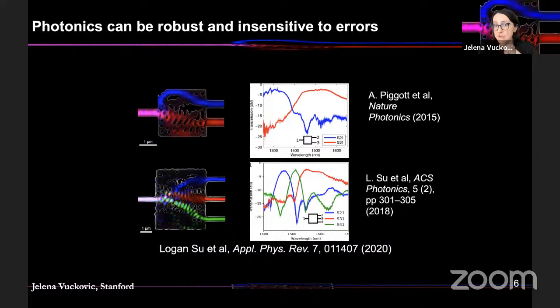And we were successful in that. Actually, here on the right, you see demonstrations. So these are measured transmission characteristics for many different devices of this type, fabricated with the same parameters. And although our process is not perfect, we don't really need to tune any of these elements. When we measure transmission characteristics and plot them together on the same plot, they all line up on top of each other for both of these blocks. So that was really exciting for us.